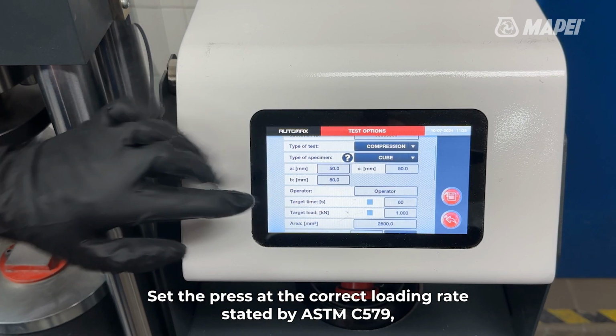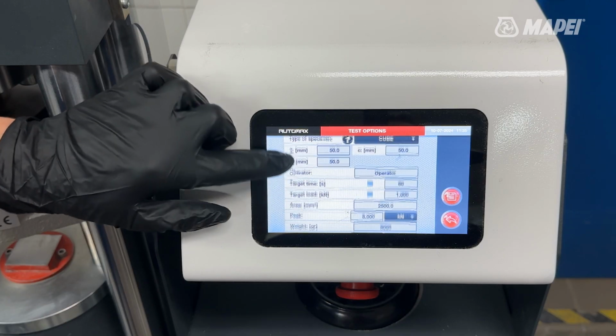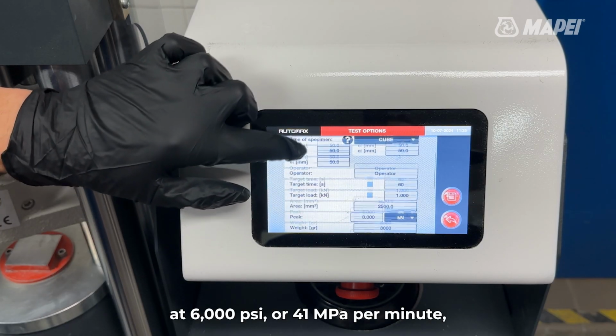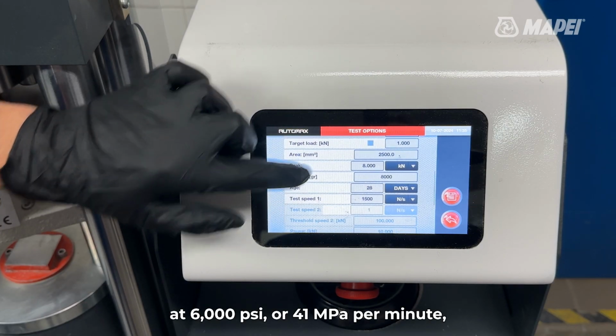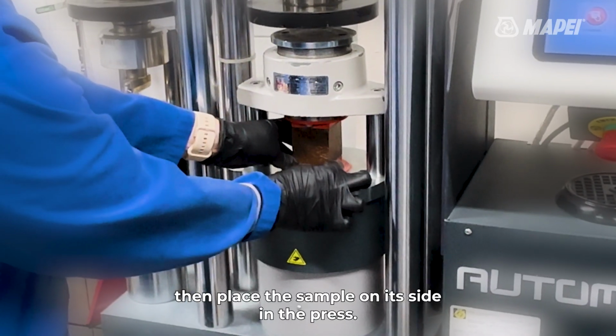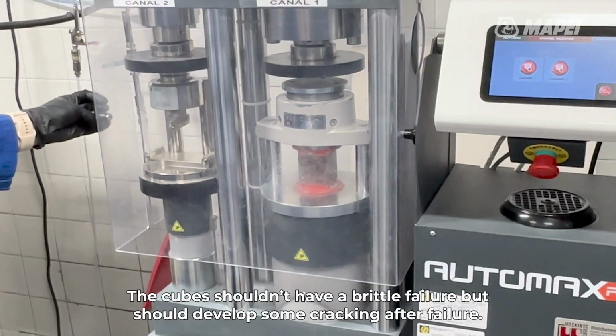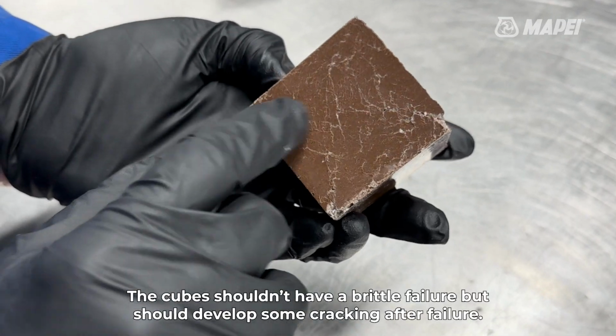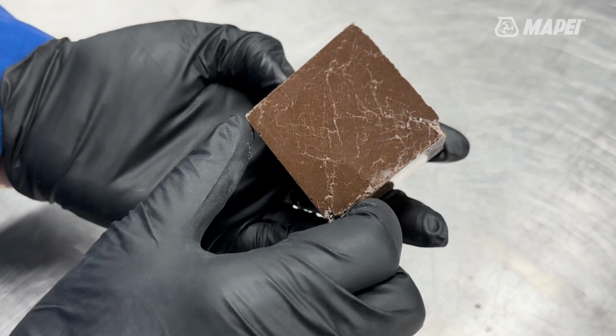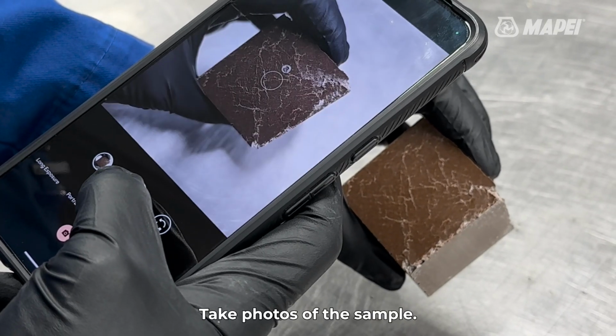Set the press at the correct loading rate stated by ASTM C579 at 6,000 psi per minute or 41 megapascals per minute. Then place the sample on its side in the press. The cubes shouldn't have a brittle failure, but should develop some cracking after failure. Take photos of the sample.